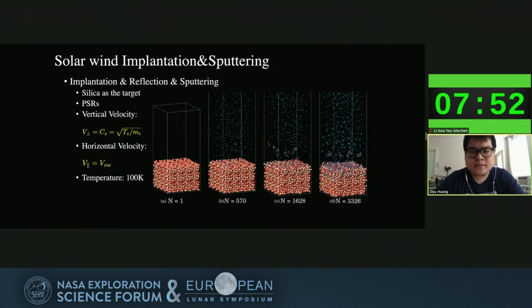We'll limit the case to PSR, since there's no photo disruption and the temperature is low, so the thermal disruption is low as well. The horizontal velocity is the drifting velocity of solar wind, which is about 400 kilometers per second. And the vertical velocity is calculated by the plasma sheath theory, which is the ion acoustic velocity, the square root of electron temperature over the mass of protons. And the value is about 40 kilometers per second.